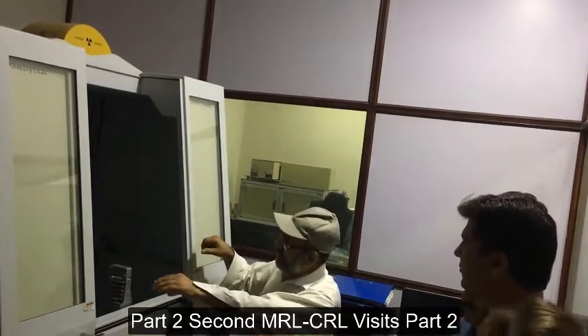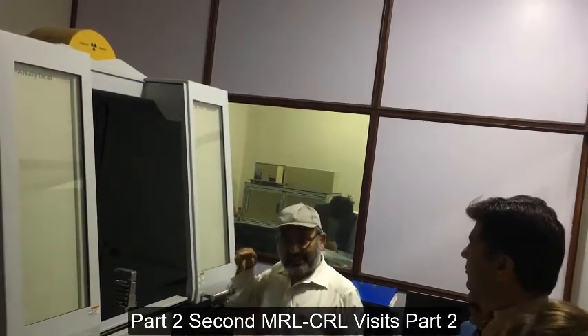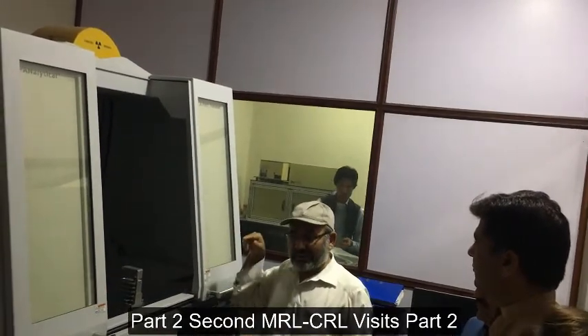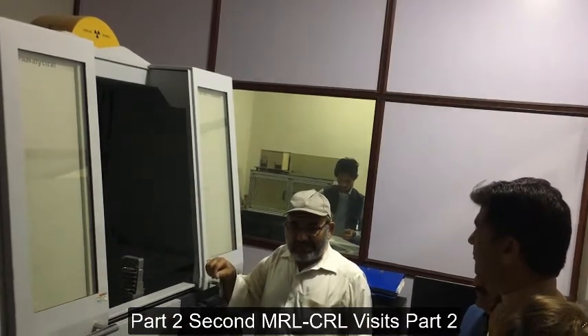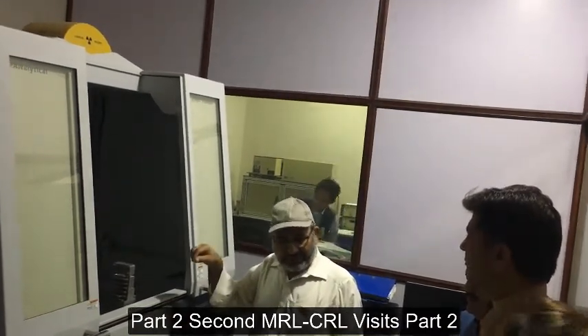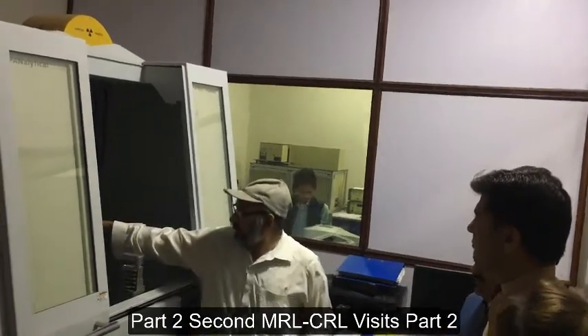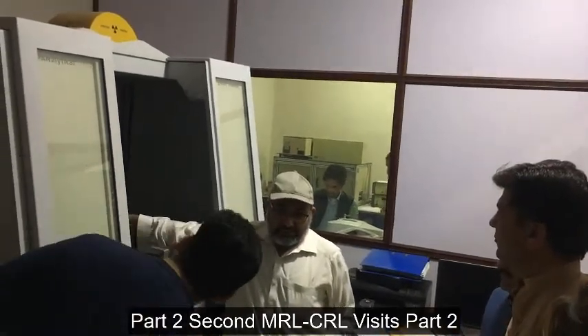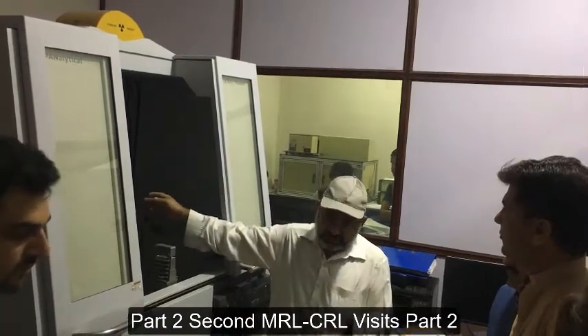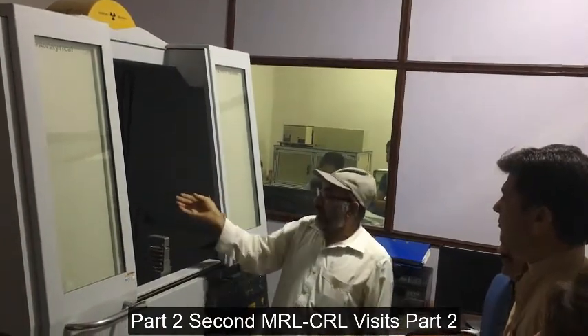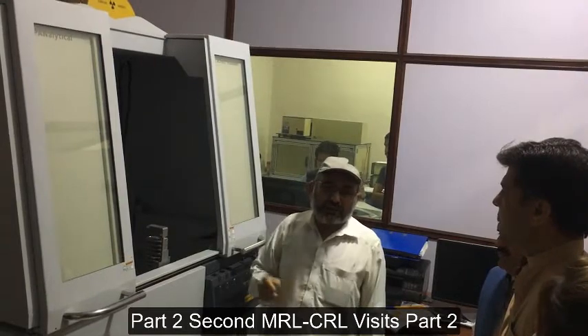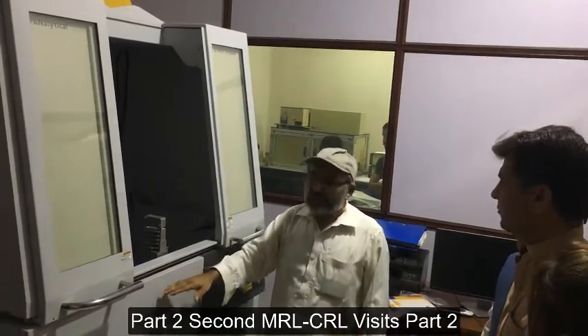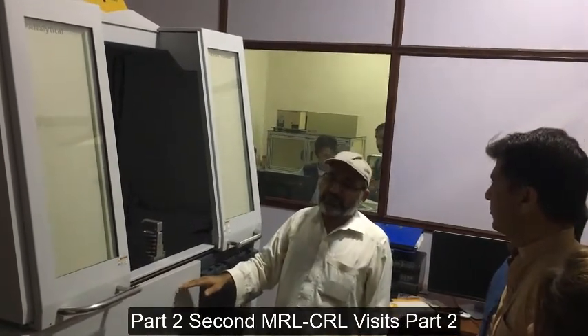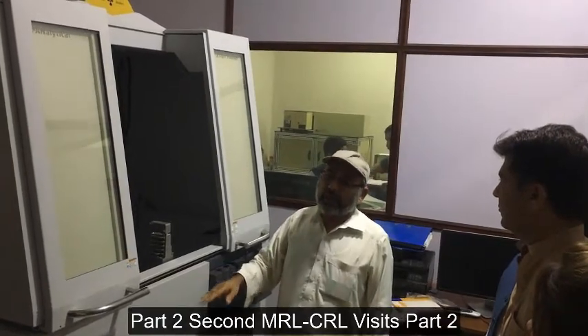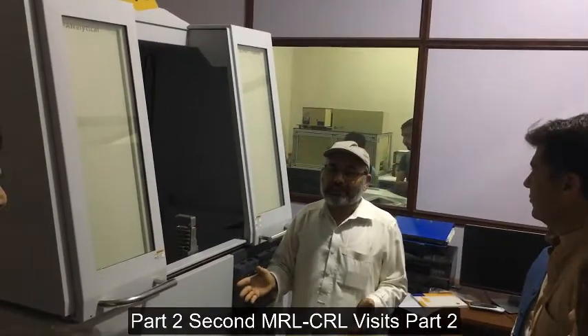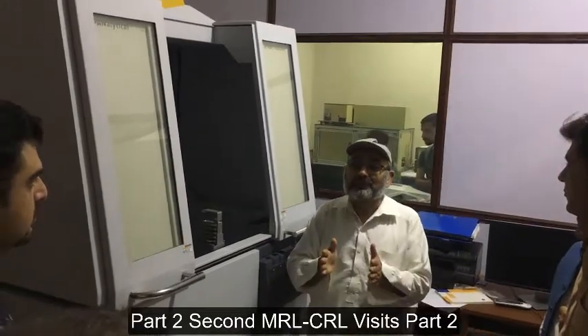On one side it has a detector, on the other side it has an X-ray source. The X-ray comes from the source and is scattered from the material. The sample is here. You see, this is a back field or front field sample holder, and the scattered X-rays are collected by the detector, and they give you 2 theta angle versus intensity, and from that you measure the interplanar spacing, and interplanar spacings are basically the walls of the unit cell.